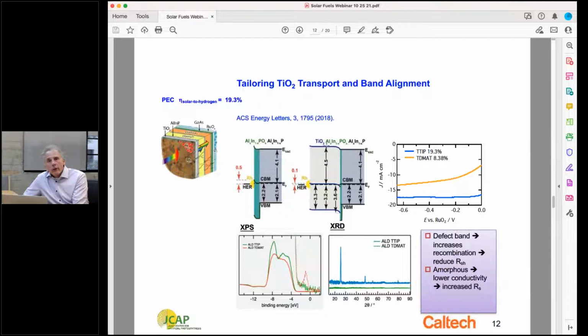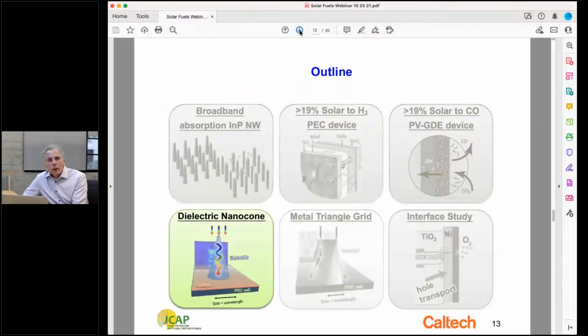Also, this coating smooths out the spikes in the semiconductor band edge that would otherwise present effectively a resistance to electron transfer to the rhodium HER catalyst on the surface. So this interfacial layer of titanium dioxide plays a role as a protective coating and AR coating, and also smooths out the band alignment in the tandem photoelectrode.